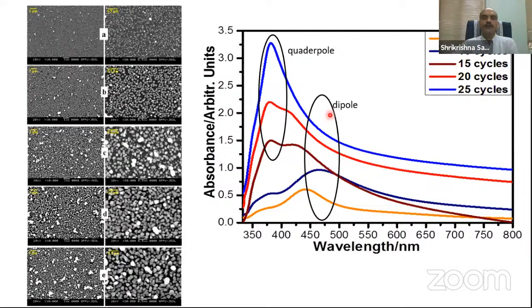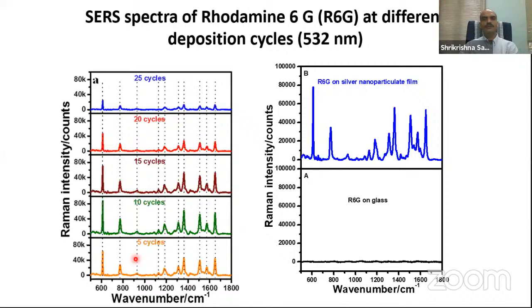So these dipoles will give you that. You get these dipoles when they are spherical nanoparticles. If they are not spherical, you get this quadrupole. And what we have seen is that this information is useful for us, because we have seen that the surface plasmon resonance peak appears at different frequencies, and accordingly we can see that for 10 cycles you get very high intensity.